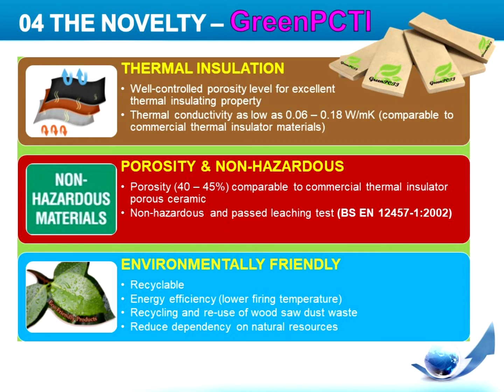On top of these successful inventions, we would like to precisely highlight and emphasize that the novelty and uniqueness of these inventions are based on three criteria. Number 1, thermal insulation. The Green PCTI has well-controlled porosity level, leading to its consistent and lower thermal conductivity of as low as 0.06 watts per meter Kelvin.